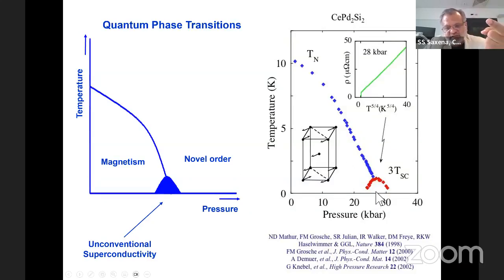But the other important thing, which is as important as superconductivity, is the state above superconductivity, the normal state. If you are a specialist, you'll notice immediately that the power law 5/4 represents a deviation from the Fermi liquid picture, which should be T squared. So for the newcomers, what does that mean? It means that in a normal metal, when you go down to lowest temperatures, once all the thermal fluctuations have become very low in energy or are not present, and the material is clean enough that there are no defects, the only thing you have left is the scattering of electrons from each other. That manifests itself in quadratic behavior in temperature, T squared. And that's the standard model of condensed matter physics, the Fermi liquid theory.